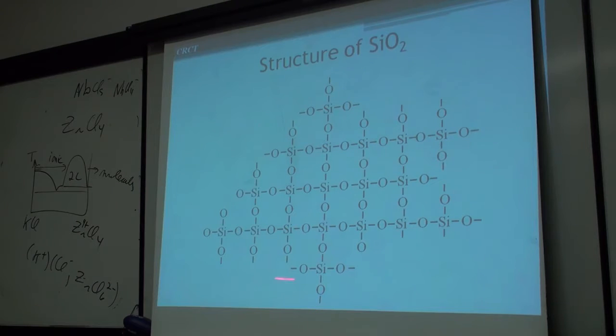No matter what you add to this now, calcium, magnesium, whatever, you're not going to change the fact that the silicons are bonded to 4 oxygens. And these, as far as I'm concerned, are covalent bonds. They may have some slight polarization towards the silicon, but I think to call that a silicon 4+ is just the valence. These are covalent bonds. They're sp3 orbitals towards the corners of the tetrahedron, period. That's all you find.